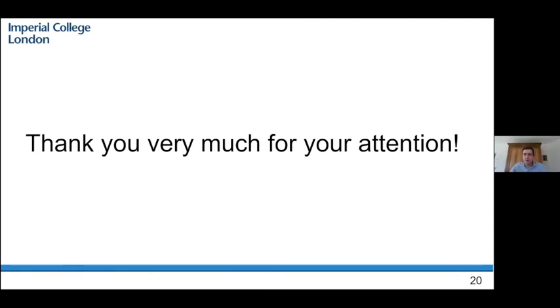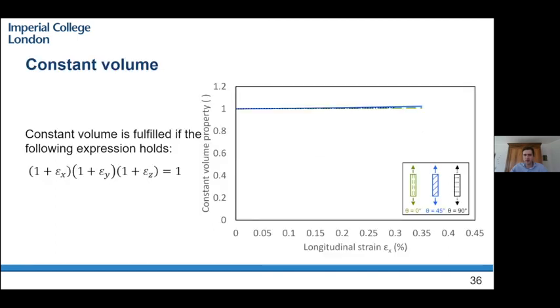Yeah, sure. Thank you very much for your question. So for the through thickness directions, that's a good point. Definitely we have analyzed it, and because DIC does not have the best resolution in the through thickness direction, the results were rather noisy. However, you can see, for example, here where we analyzed the volume of our coupons using the three strains to check if constant volume is still fulfilled. And you can essentially see that the through thickness measurements were stable enough to see that the constant volume is more or less conserved over the whole longitudinal strains.